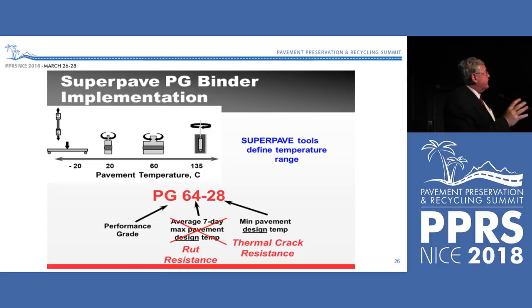The software is different. Intermediate temperatures, we had a parameter called G*sin delta. It was supposed to be a fatigue parameter. After 20 years, we found out that didn't work, and pavements are cracking because that allowed too much recycled engine oil, and that was a really bad thing. And so that's one of the things we're working on, trying to understand cracking in the context of rheology. And with black space, we're getting there. And you can refer to some of those papers elsewhere.